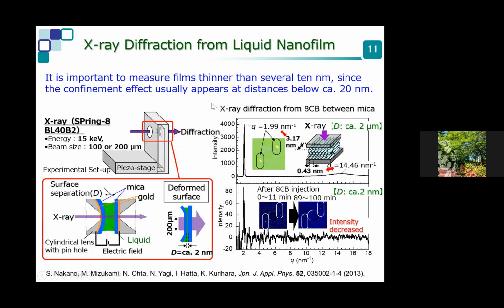We believe this is the first example of an X-ray diffraction study from nanometer-thickness liquid. We took the same setting as that group, but tried to accumulate signals and improve them. But at that time, we did not know how to regulate different gaps at small distances. So we did two cases, at 2 micrometers and 2 nanometers. This is a very compressed, hard-wall thickness. But we could obtain the scattering spot like this, although it relaxed to no clear X-ray diffraction spot after 100 minutes.